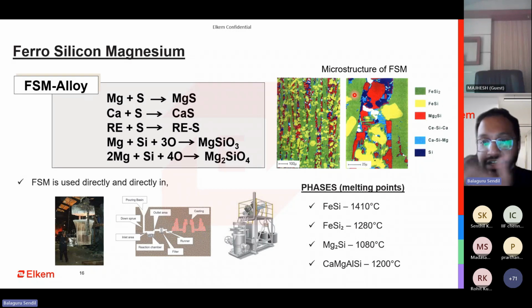You might get a ferrosilicon magnesium at a cheaper rate, or you might get a substandard product where you would not see this much magnesium. You would see a lot of it being spent only here. The distribution is completely segregated. You will not see Mg2Si or calcium, magnesium, aluminum silicide. You will just see magnesium segregated out. Because of the way they produce it, it will again not perform as well as a uniformly distributed one. So this is the FSM alloy.